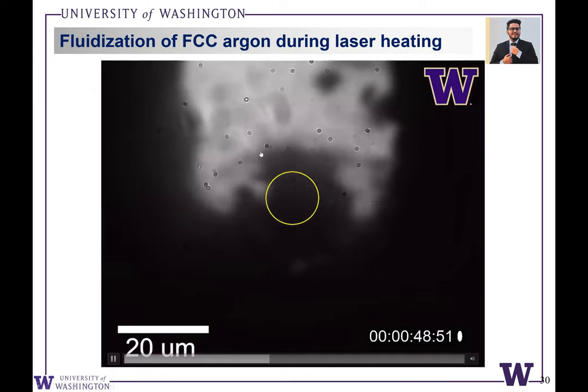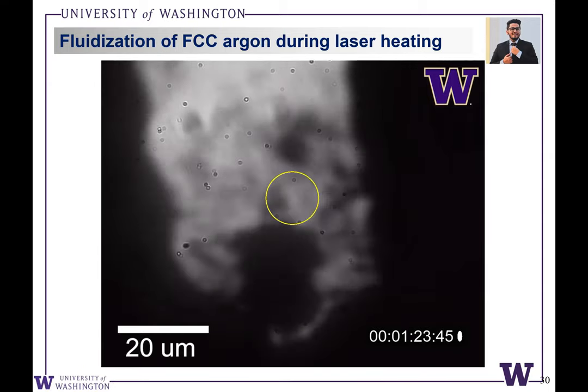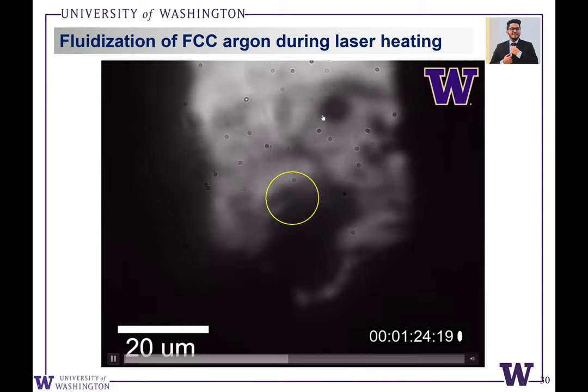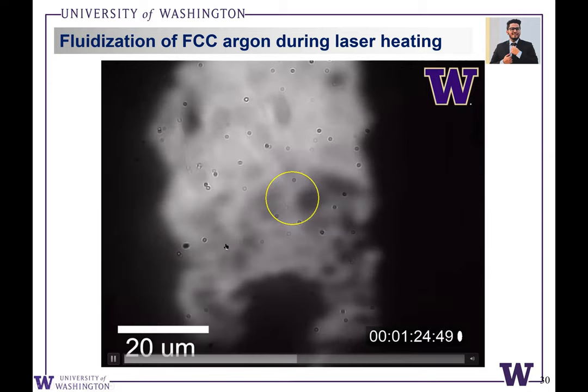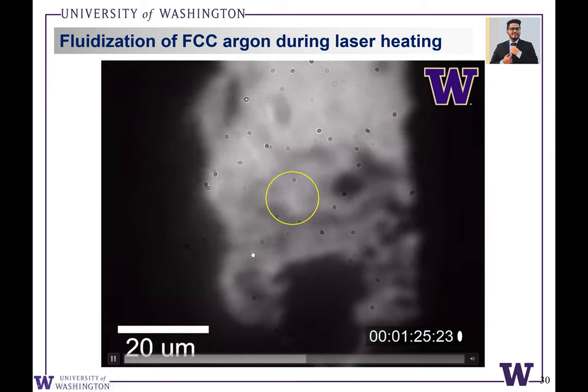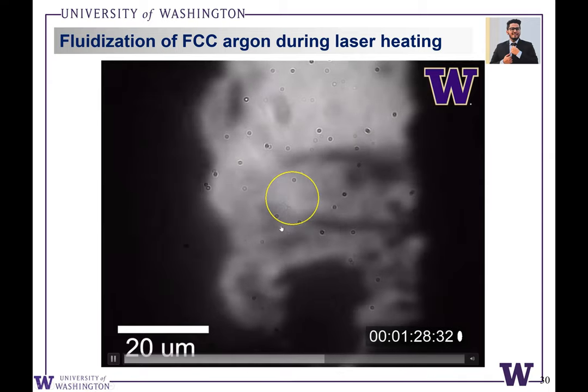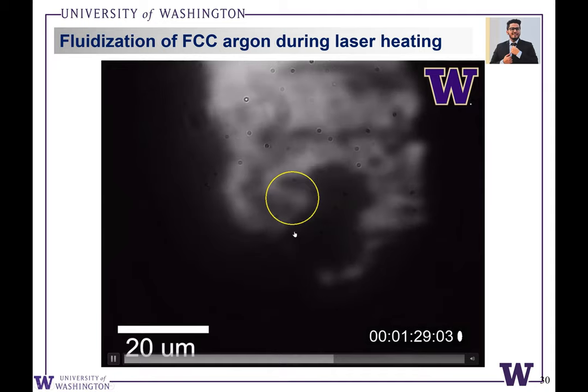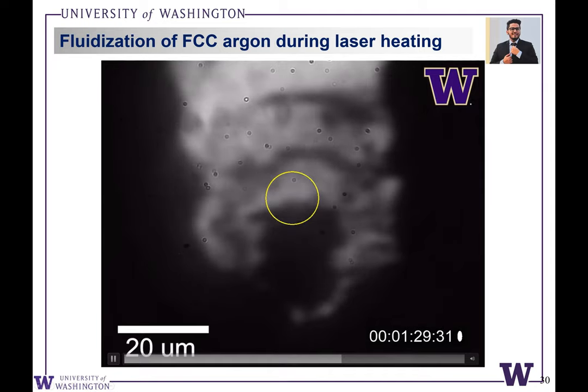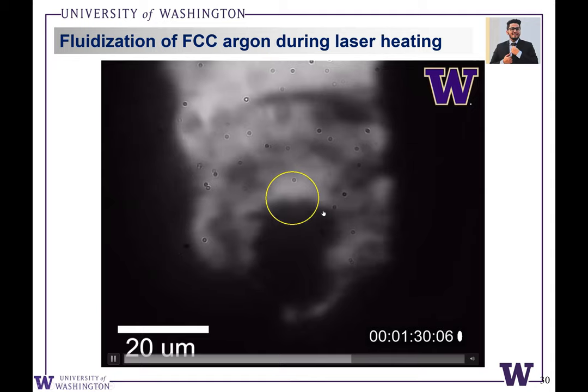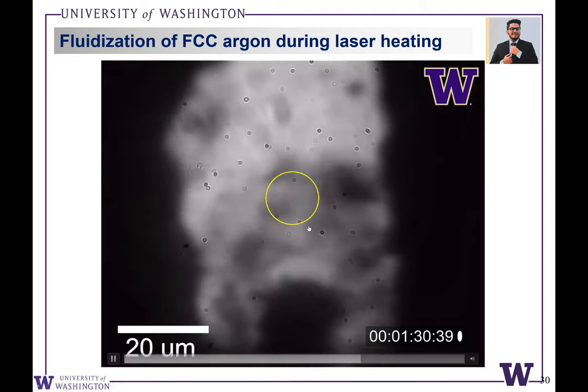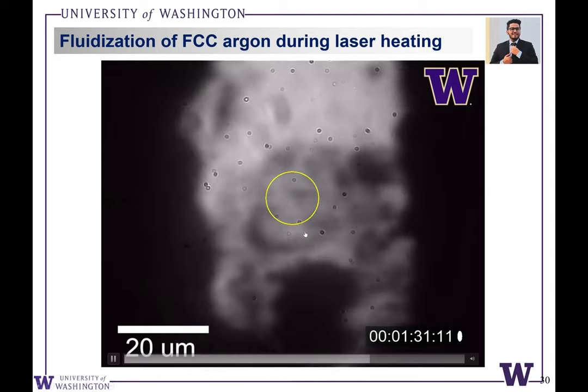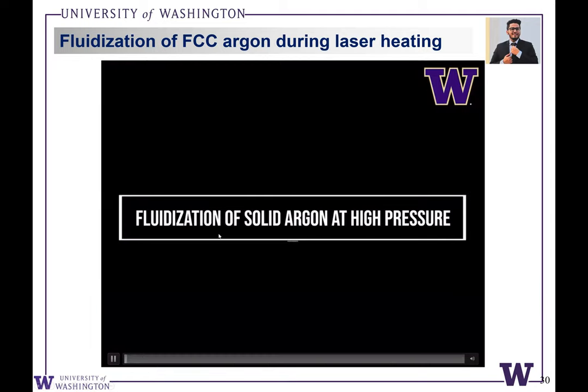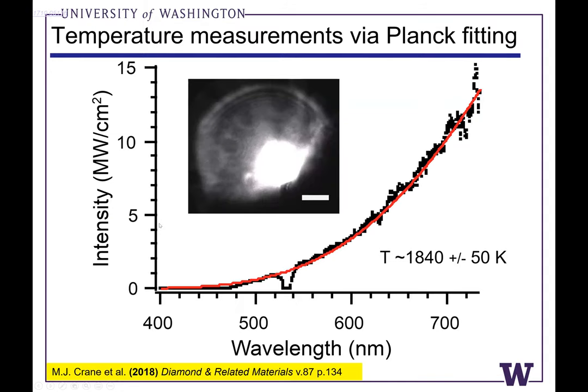propagating. And we started to wonder, maybe as we were laser heating, at longer time points, you can see how the carbon material can decompose, it can propagate throughout the cullet at extreme conditions. We started to hypothesize maybe the atoms of argon were able to dissolve or diffuse within the micropores of the aerogel and effectively get trapped in the lattice after they were fluidized. So we started to really scratch our heads and wonder, is this possible?